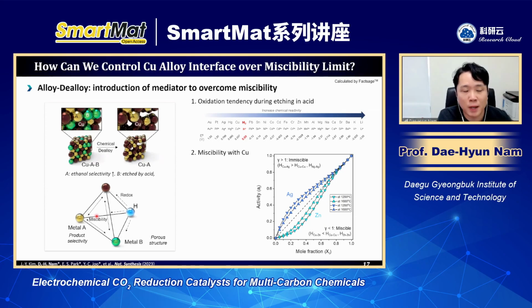So we had an idea of applying an alloy and dealloy strategy. Instead of directly mixing copper and silver together, we can apply a third element which can be dissolved into the copper and silver together. After we have this ternary phase alloy, we can selectively etch these B atoms, which are used as a sacrificial one. By designing this ternary phase alloy, we have a chance to make a solid solution copper-silver alloy through this alloy-dealloy process.